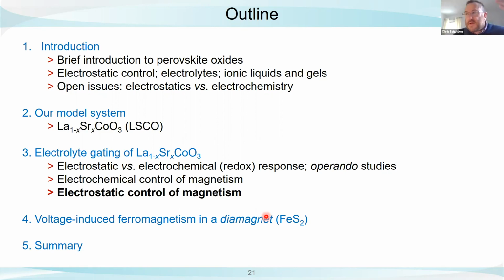Once you generate with an electric field some oxygen vacancies on the top surface, if the diffusivity is big enough, they will proliferate. If the diffusivity is low, they won't. And this seems to sort of jive with everything that's in the literature. And in that context, the cobaltites are very attractive. Manganites don't have as high an oxygen vacancy diffusion rate. The other systems that can have very high oxygen diffusivity, interestingly, are cuprates. So for instance, in the 214 lanthanum strontium cuprate, that can have very high oxygen diffusivity, even at room temperature. So we think that's the key variable.